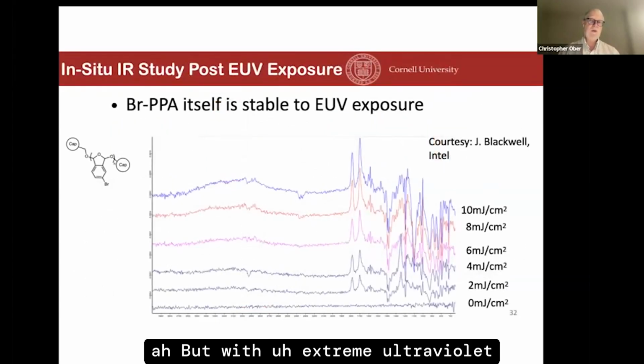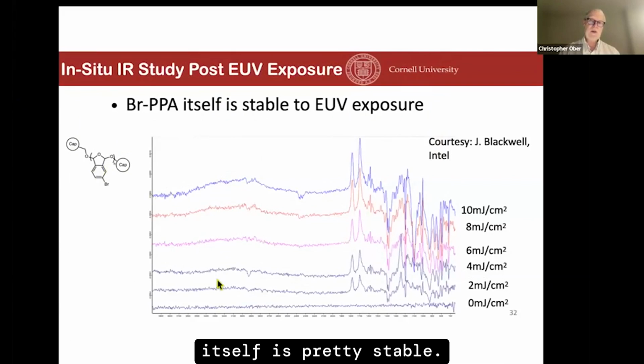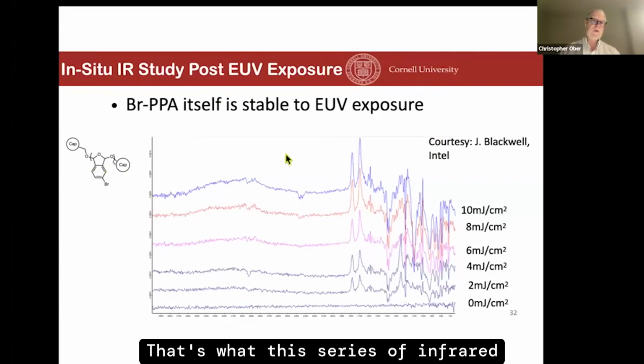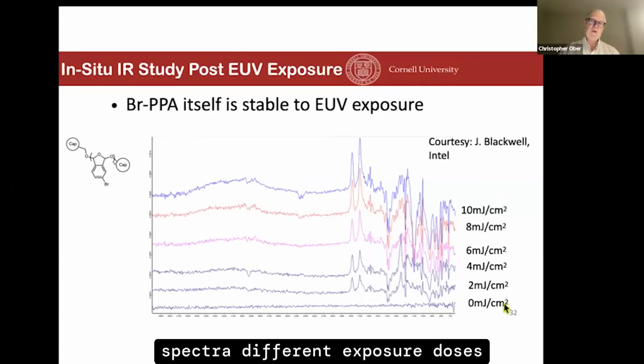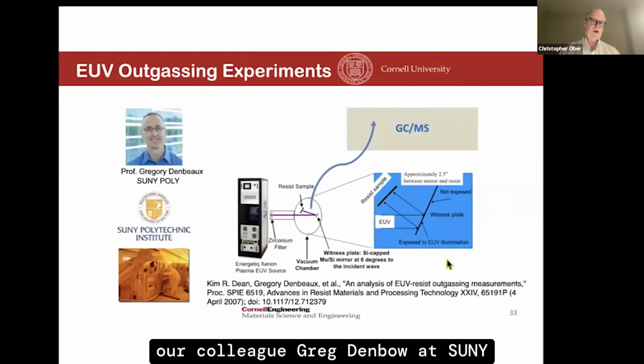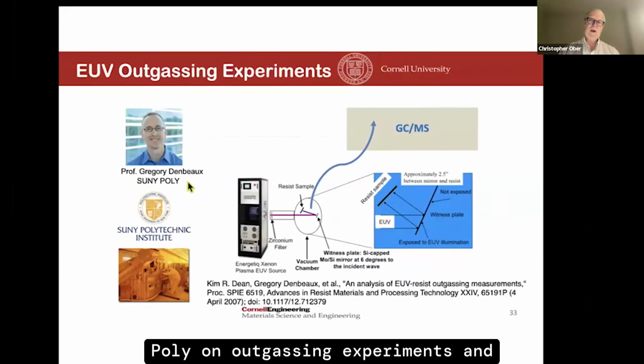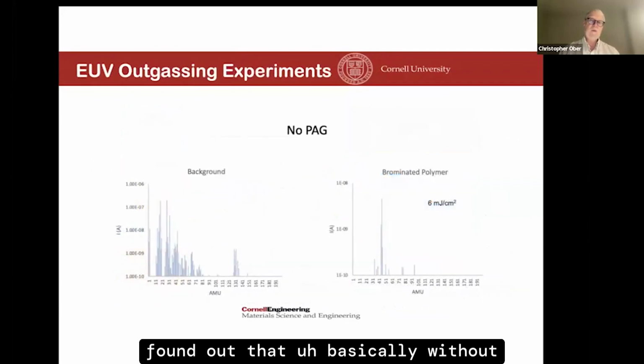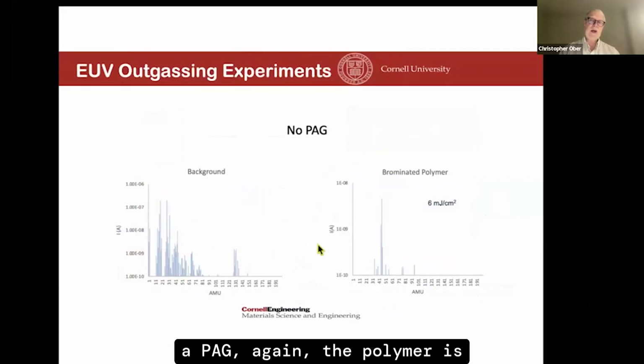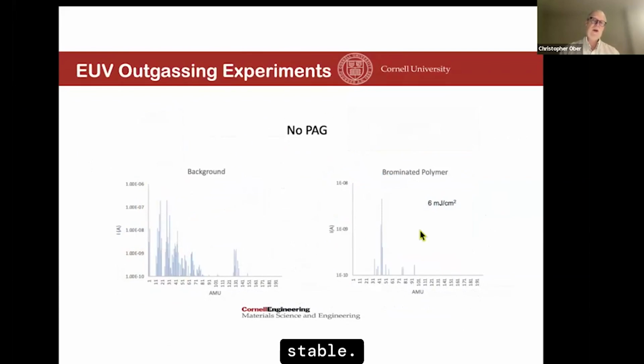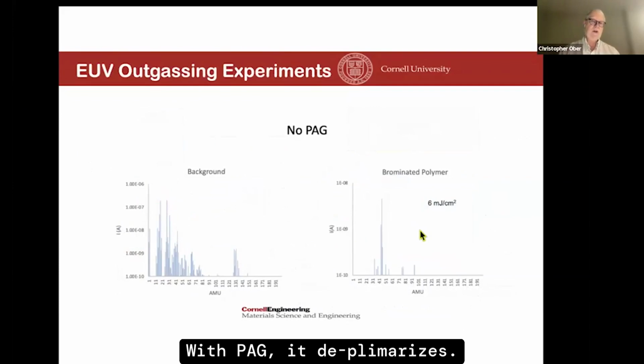But with extreme ultraviolet exposure, it turns out the polymer itself is pretty stable. That's what this series of infrared spectra at different exposure doses tell us. And we looked with our colleague Greg Denbeaux at SUNY Poly on outgassing experiments and found out that basically without PAG, again, the polymer is stable. With PAG, it depolymerizes. It goes back to its original building blocks.